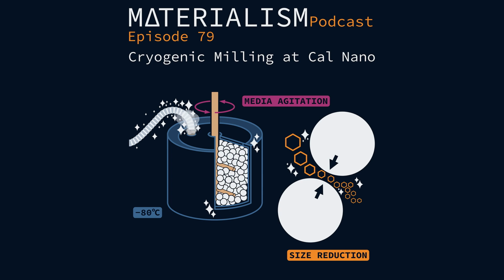And in general, the faster milling times are going to come with your more dense media, right? So I know that in my lab, we've often used tungsten carbide media, which is not cheap. And it's better if you have a tungsten carbide container, right? But these are not cheap to buy. But that higher density just really decreases our milling time, which is something that we've enjoyed in the past.